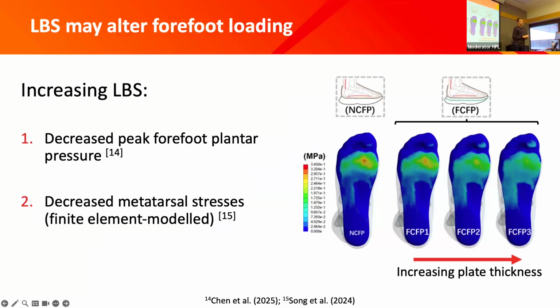So longitudinal bending stiffness has been investigated with respect to plantar loading in some modeling studies, and there are some very interesting findings on the effect that this has. If we look at this study here, essentially what they did was a finite element model of the plantar pressure in a bunch of different conditions. In the far left condition here, this is the shoe with no stiffening element in it, so no carbon fiber plate. You can see this is the plantar pressure distribution they get, where red is high and blue is low. So under the metatarsal heads here, you can see some high pressure happening.